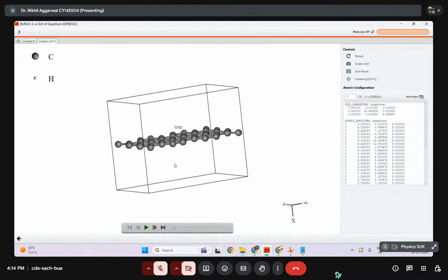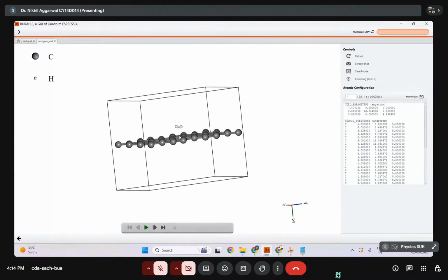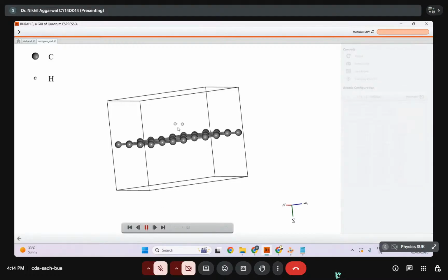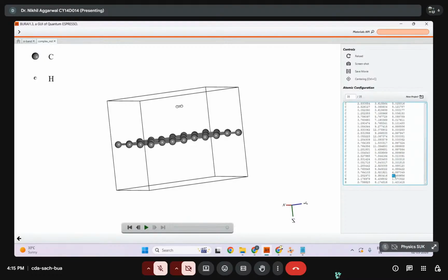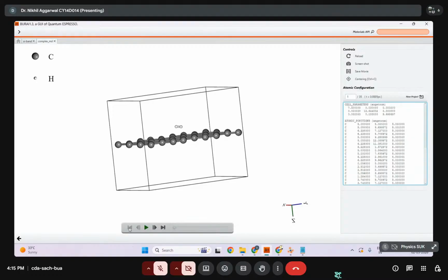See, this is the initial structure which we took for the MD studies. At 1.4 angstrom, I was a little skeptical that there would be an intermolecular repulsion. And when the calculation started, the hydrogen molecule went far from the graphene layer so as to minimize the repulsion and maximize the attraction, and finally it reaches this distance. At this particular distance, I can see the distance is around 3.6 angstrom, and 3.6 angstrom is a pretty good value for the intermolecular van der Waals interaction.